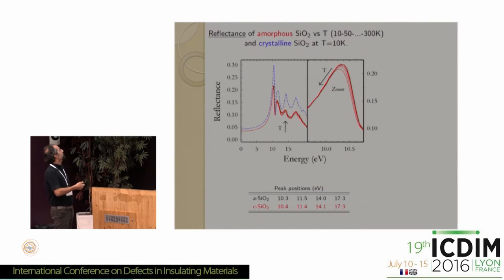This is the typical set of experimental data that you can obtain with this study. You can see on the left the reflectance of a sample of amorphous SiO2, which is red, and crystalline SiO2, which is blue, in a range from 0 to about 20 electron volts. The red measurements for amorphous SiO2 were taken at different temperatures. And you see that essentially you have a strong increase of the reflectance around 9 to 10 electron volts, which tells you that you are going beyond the band edge of the material. But it's not so easy to directly interpret the reflectance spectra.